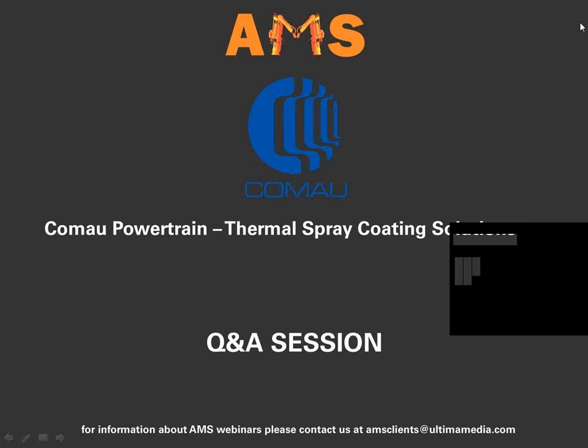It is sufficient in terms of surface contact to reduce the mechanical interlock. Then, of course, the biggest thing for us is cleanliness of the surface. When we talk about cleanliness, we require the surface really to be dry. Any residual water or coolant will cause a local steam pocket that then will create an area of delamination. The other area is any particulate or chips that are left on the surface in mass will cause an issue.